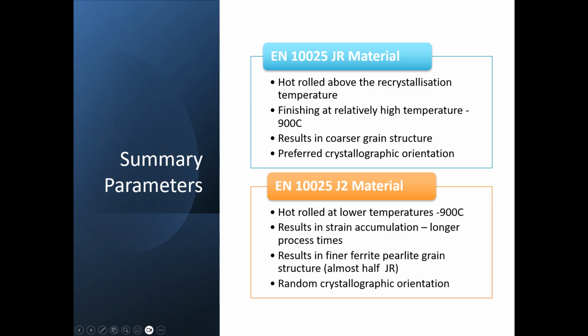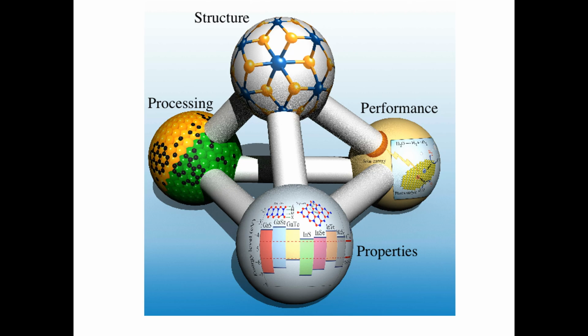J2 is hot rolled at lower temperatures than 900 degrees. And due to the strain accumulation because of the lower temperature rolling, you need a longer processing time, but this does result in finer ferrite pearlite grain structure and a random crystallographic orientation. So you can see here how the structure and the way in which you process gives you certain mechanical properties that affect the performance of the fabricated item.